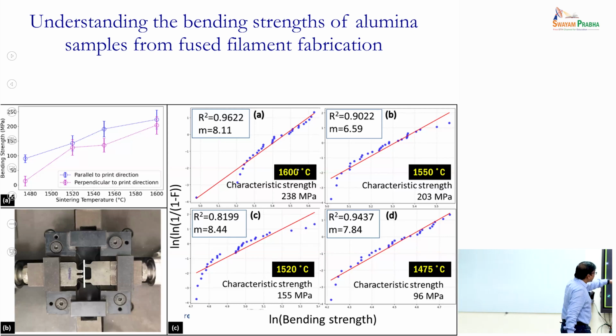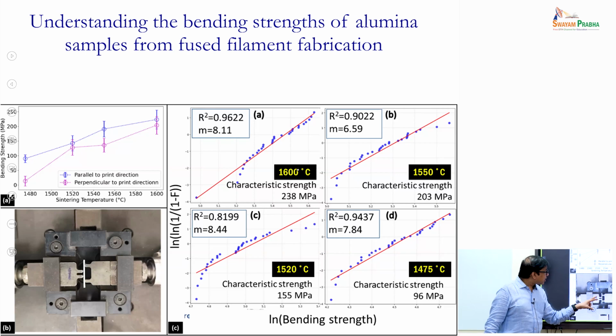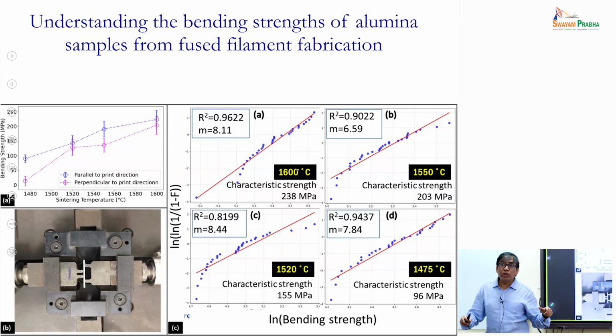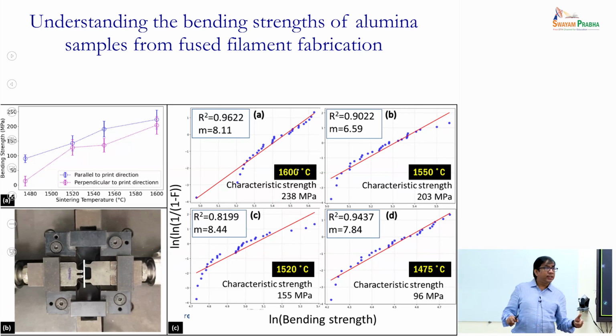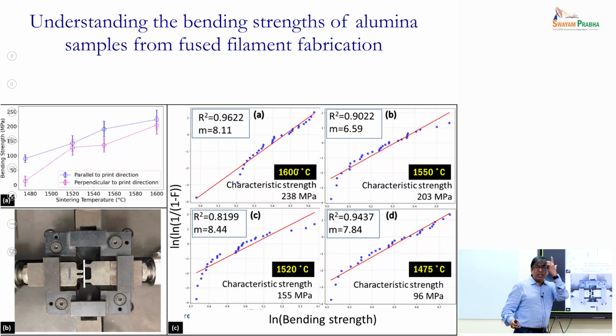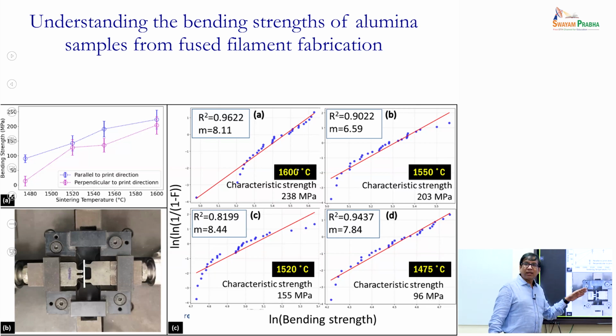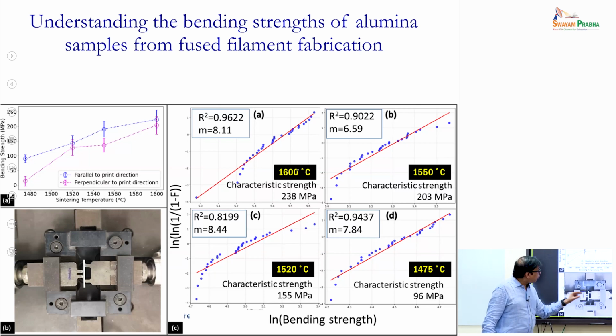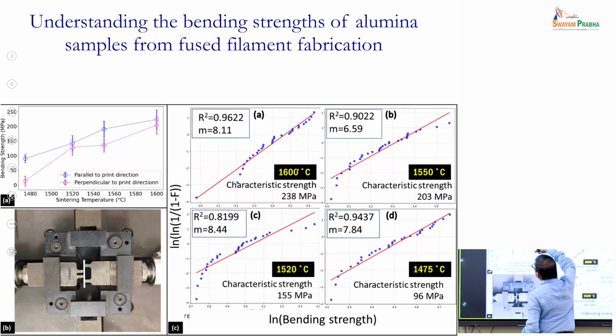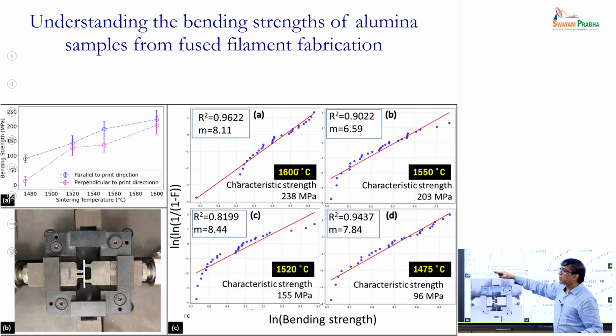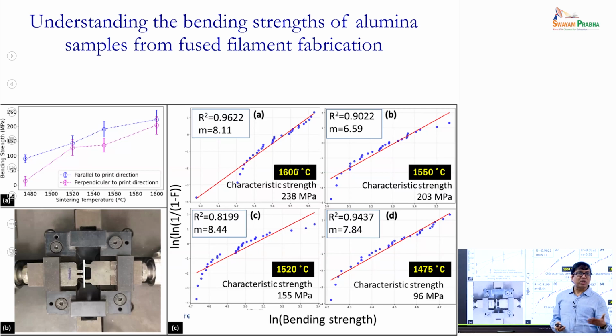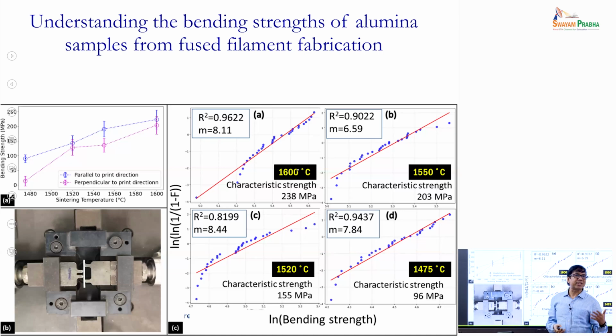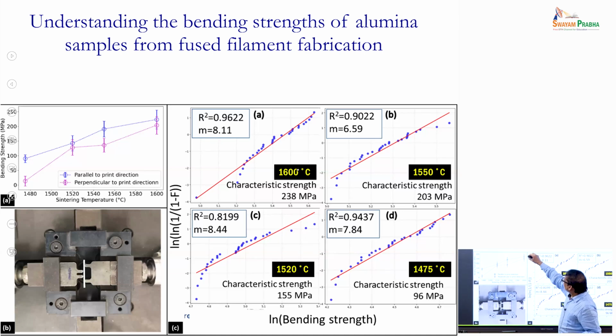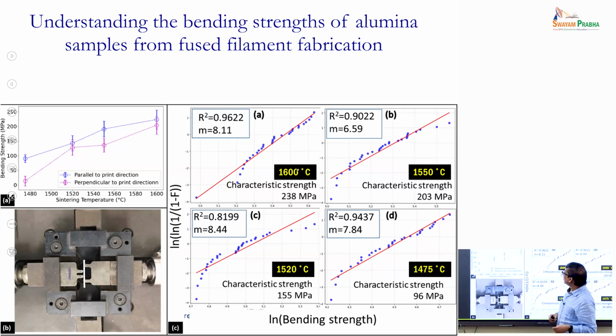What I'm using is a small scale testing technique developed in our own lab. It's a 4-point bending mode, and I've already told you why the 4-point bending mode is important and justified the 4-point bending strength technique. Now you can see it's a very small sample in 4-point bending mode, and we have measured the bending strength in 4-point mode. You can see variation. Of course, it is dependent on the microstructures, because as we sinter at different temperatures, the pore fraction is different. And obviously at higher sintering temperatures, irrespective of the printing direction, it tends to have more or less close values.